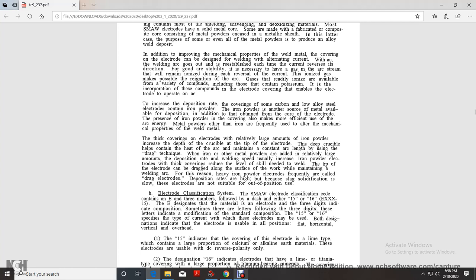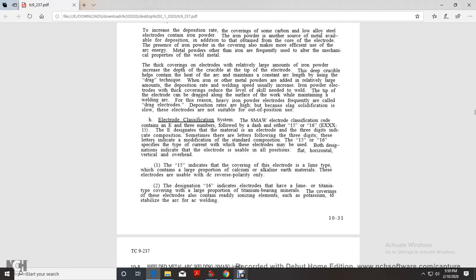Because iron and other metal powders are added in relatively large amounts, the deposition rate and welding speed usually increase with iron powder electrodes. The thick coverings reduce the level of skill needed to weld. The tip of the electrode can be dragged along the work while maintaining the arc. For this reason, the heavy iron powder electrodes are frequently called drag electrodes. The deposition rate is higher, but because of the slow slag solidification, these electrodes are not suitable for out of position use.